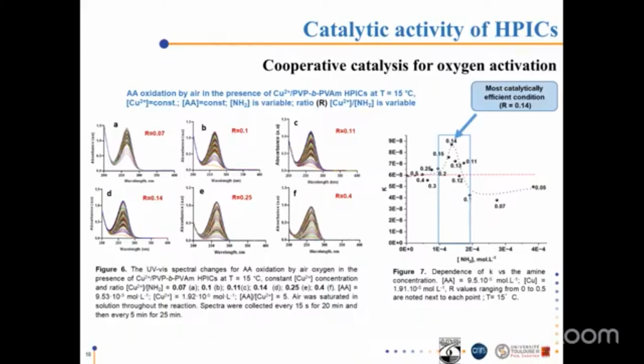When the polymer amount was enough to complex most of the copper ions present and it induced the ASH peaks formation, this is the ratio between 0.12 and 0.25, a significant increase in the rate constant is observed. And as we can see, the most effective catalytic condition shows ratio 0.14.